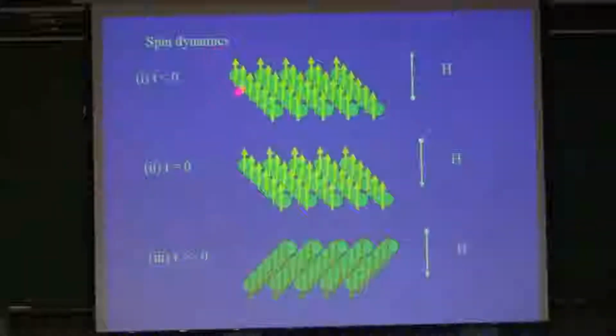Okay, the spin dynamics at that time: if you apply a field, initially everything points in this direction. But when you reverse the field from t equal to 0, then these moments will relax along the field direction. Finally, they will go to here. But in the late 80s, we didn't have enough knowledge to study the spin dynamics from here to here, because the relaxation time is from gigahertz to terahertz, 10 to the minus 9 seconds to 10 to the minus 12 seconds. So it's quite fast. No matter experiment or theory, it's not easy to analyze these things.